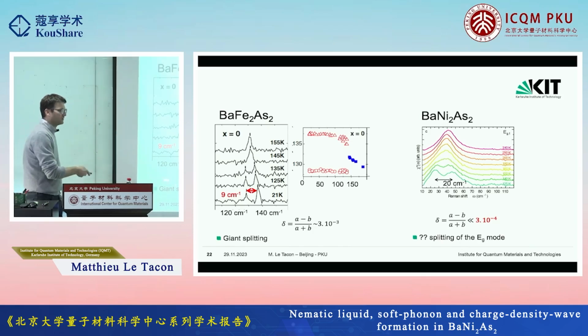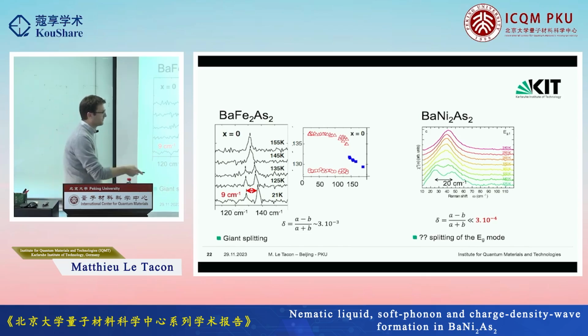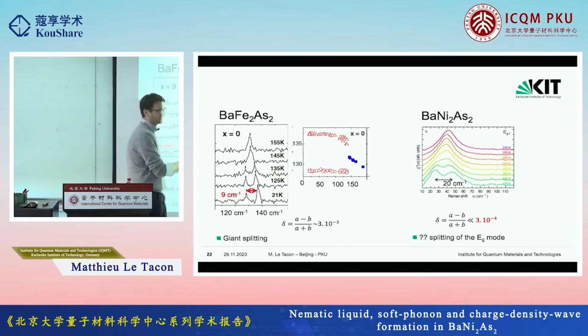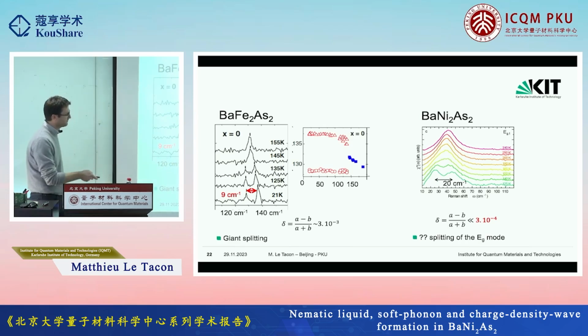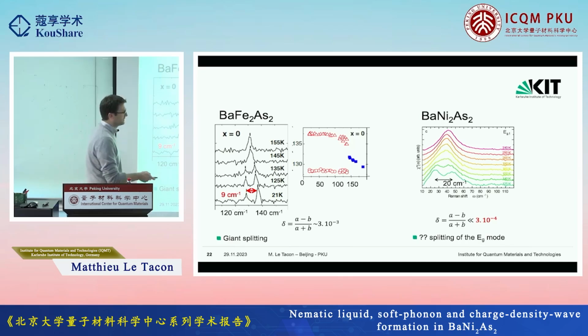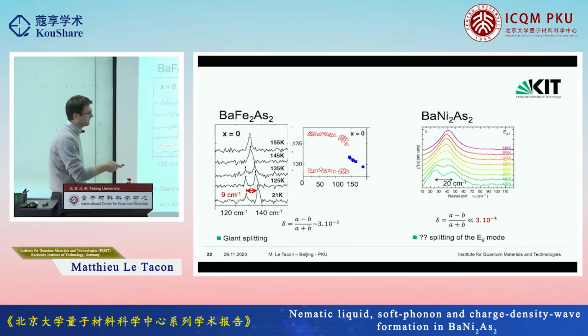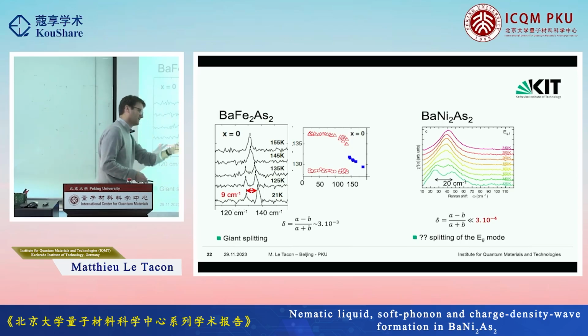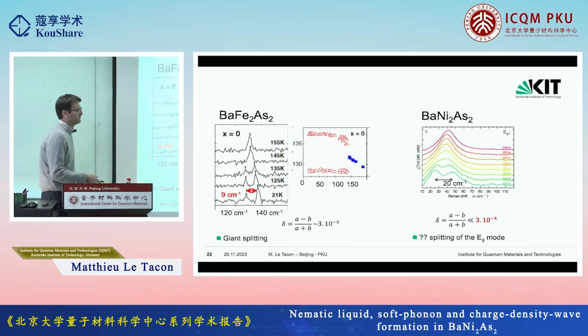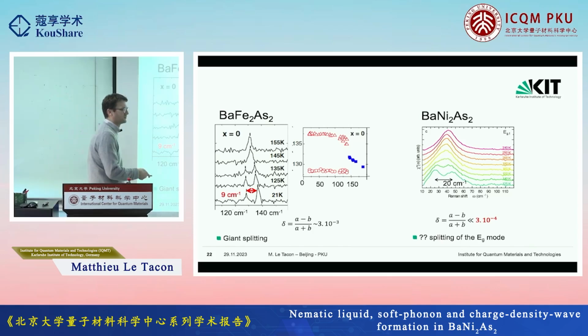In the case of the BaFe2As2, the iron compound, it was called a giant splitting. And I'm not sure what is the word we should use for this kind of splitting in that case. Because relatively speaking, you have a distortion which is 10 times weaker and an effect which is at least twice larger. So it is at least 20 times larger. And if you think in terms of relative value, which, okay, is arguably a bit cheating, it is a 50% splitting, so it's an order of magnitude larger effect. 2 orders of magnitude larger effect, sorry.